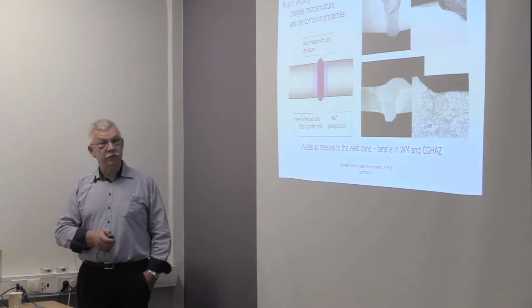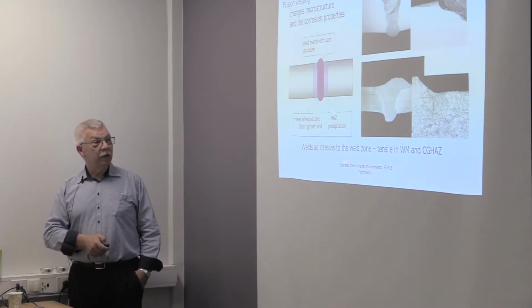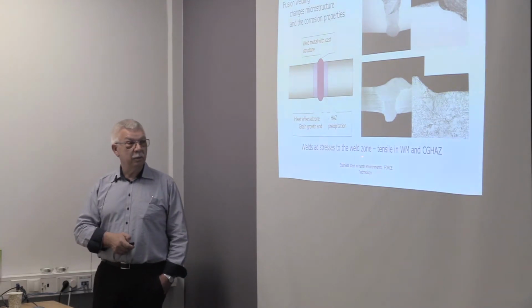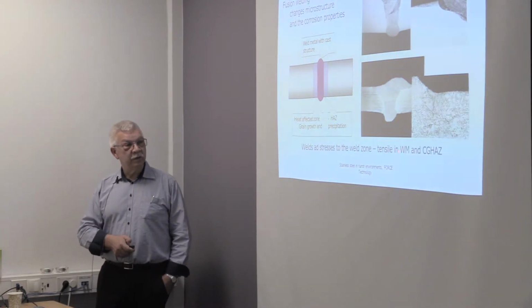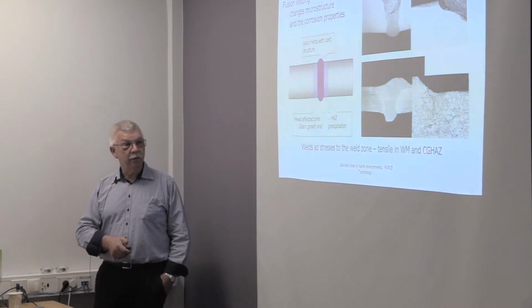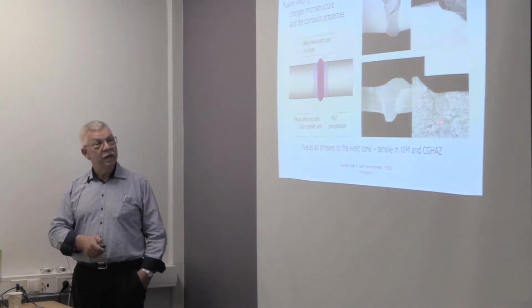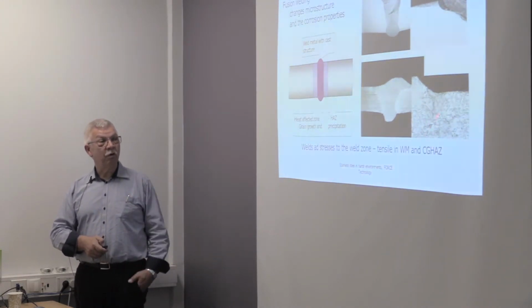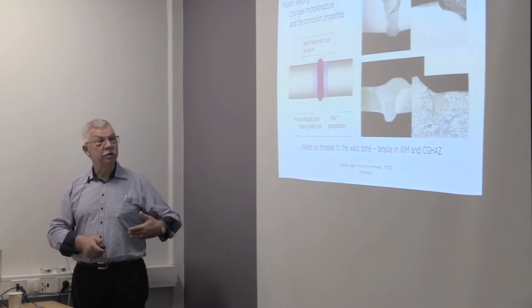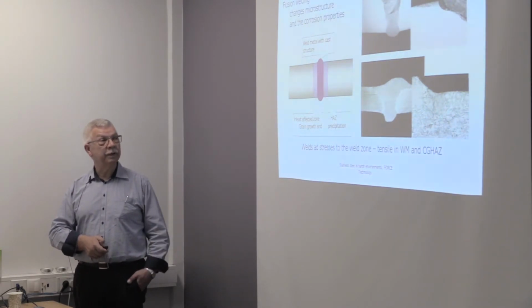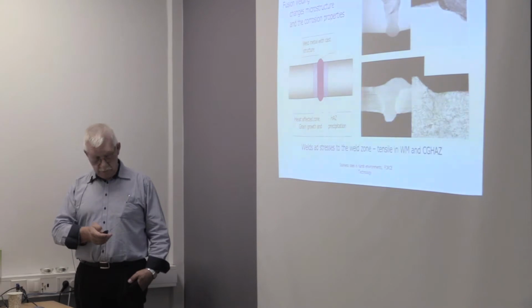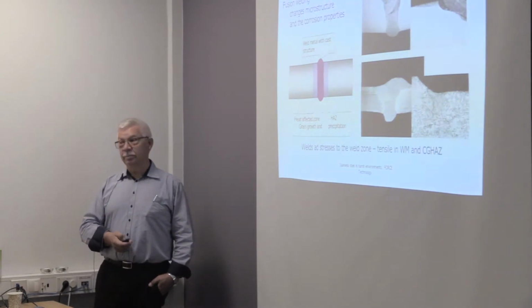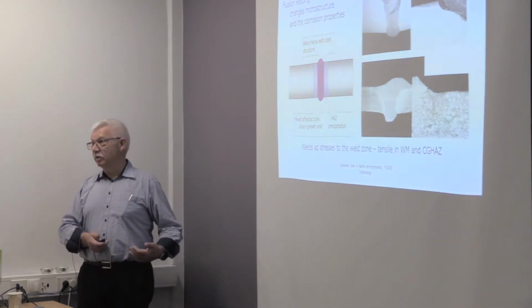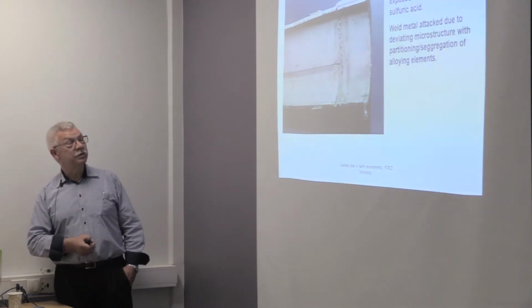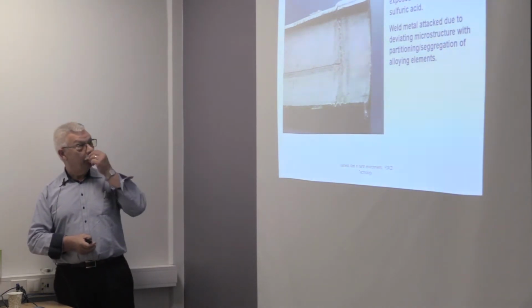And of course, as we saw with stress corrosion cracking, welds will tend to give stresses in the weld zone, tensile stresses in weld metal and in the coarse-grained heat-affected zone, there where we have the risk of stress-induced corrosion, like stress corrosion cracking. So welds will generally be a weak point from a corrosion resistance point of view.